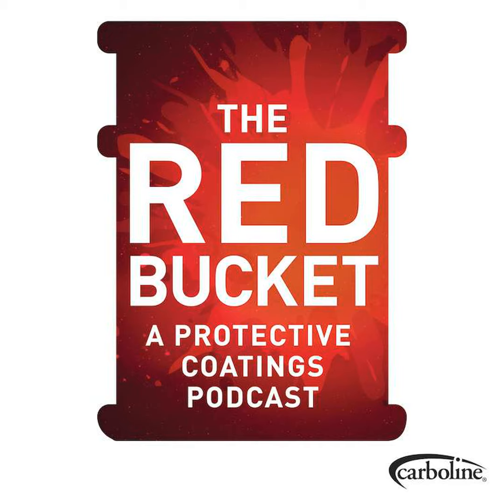But really, what I love is urethane cements. You're putting a cement on a cement. Historically, urethane cements are unaffected by moisture vapor transmission, and I think it has to do probably with the porosity of the urethane cement itself. Yes. And so it gives a place for that moisture to go. The epoxies are rigid. They're tightly cross-linked. They're too dense. They're too dense.